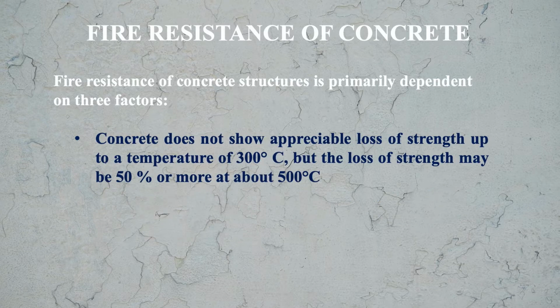Concrete does not show appreciable loss of strength up to a temperature of 300 degrees centigrade, but the loss of strength may be 50% or more at about 500 degrees centigrade. So this is the effect of heat: up to 300 degrees centigrade not much effect, but at 500 degrees centigrade you see the loss of strength up to 50% or more. So this way we have discussed the durability, how it is affected by various factors, external factors as well as internal factors. So this way we have understood the durability.